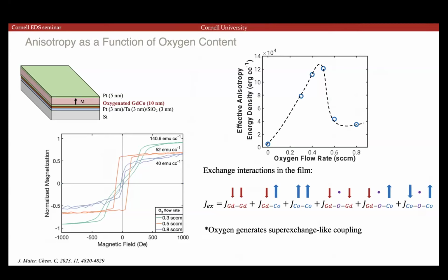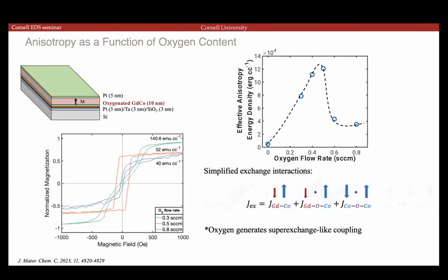is interacting with gadolinium, or gadolinium is interacting with cobalt, cobalt with cobalt, or any of these mediated through an oxygen sitting in between. In this case, when there's an oxygen sitting in between, that's where we see super exchange, and the strongest interactions were found to be only the gadolinium cobalt, the initial antiferromagnetic interaction, as well as the gadolinium oxygen cobalt and cobalt oxygen cobalt. So in the end, we can understand the material and try to increase the antiferromagnetic interaction of this gadolinium oxygen cobalt interaction by optimizing the oxygen concentration within the film.